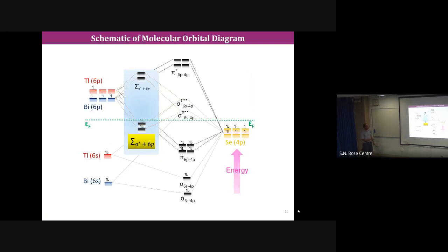So then we have drawn this MO diagram. My student and I spent many days to draw this MO diagram, because basically this bismuth 6s and thallium 6s lone pair first interact with the p orbital of selenium and form this antibond. And from this antibonding, it actually interacts with the p orbital of thallium and bismuth. This is called secondary orbital interaction. If you know the MO diagram well, then this level comes just below the Fermi level with anti-bonding character. So this anti-bonding electron filling actually gives this property in this compound.